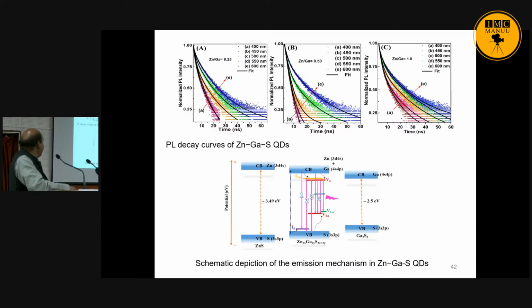So we conclude here, zinc sulfide has a band gap of about 3.49 electron volt. For gallium sulfide, the band gap is 2.5 electron volt. But if you take zinc, gallium and sulfur, the band gap is about 3.1. So this is good for photovoltaic application because this is showing different values. So these things are here.